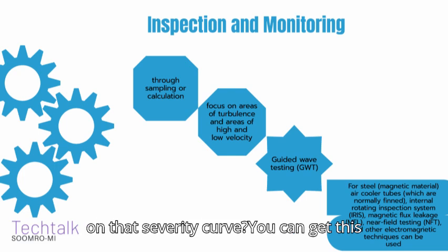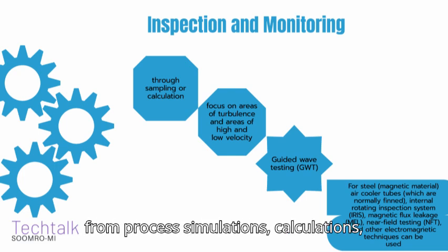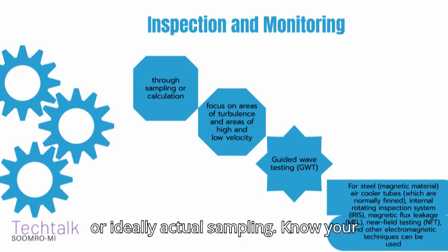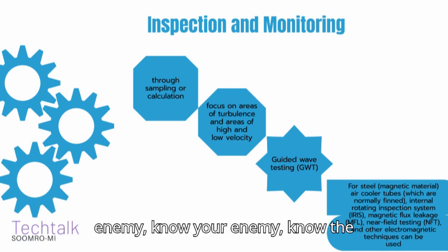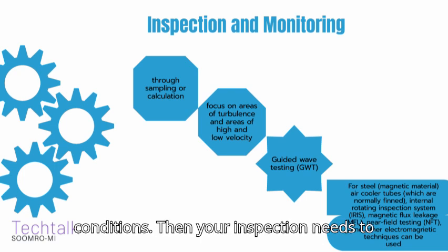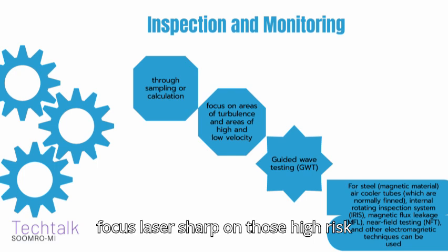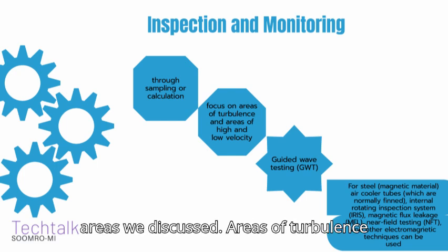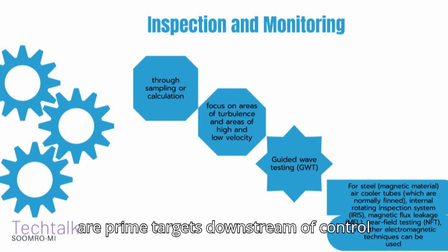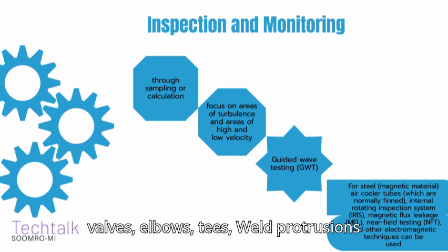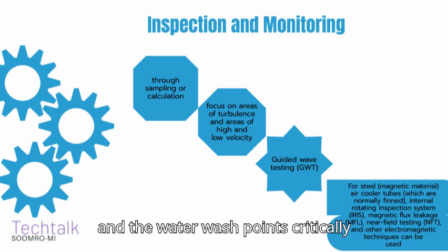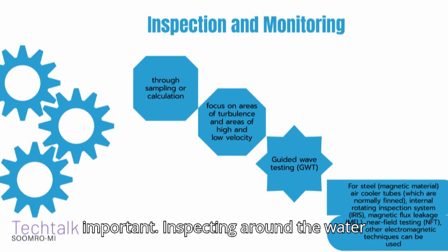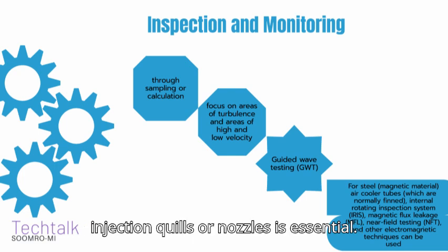Where are you on that severity curve? You can get this from process simulations, calculations, or ideally actual sampling. Know your enemy, know the conditions. Then your inspection needs to focus laser sharp on those high-risk areas we discussed. Areas of turbulence are prime targets: downstream of control valves, elbows, T's, weld protrusions. And the water wash points. Critically important. Inspecting around the water injection quills or nozzles is essential.